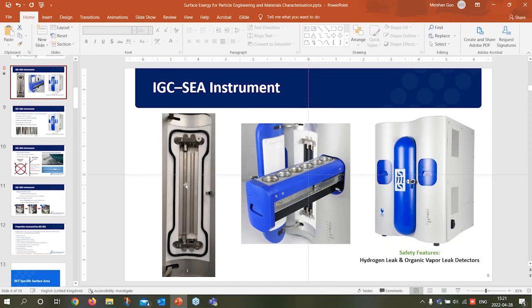Unfortunately, that's the limitation of the system itself. So we have a fixed amount of the probe molecule we can inject into the system. So the highest limit for the surface area we can measure is 100 square meters per gram. But for higher surface area material, we cannot measure the surface area, but we can still measure the surface energy of that material by inputting the BET surface area beforehand from another technique.